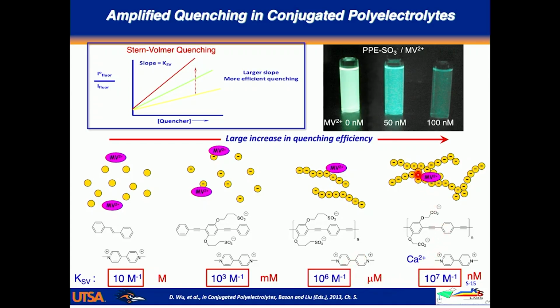And it turns out under certain conditions where these polyelectrolytes are aggregated, which is pretty common, you can see these Stern-Volmers go into the range of 10 to the 7th to 10 to the 8th. So you can get really, really high quenching constants. And that now means that in terms of sensing, you can detect things like this viologen in the low nanomolar range. And just to give you an idea, visually what this means, this is our polyphenylene ethynylene sulfonate. These are actual photographs of solutions of that polyelectrolyte with 0, 50 nanomolar, and 100 nanomolar viologen. And you can see quite visible quenching, which is very easily detectable by using spectrophotometers. So this is the idea of amplified quenching. It allows you to measure these effects at really low concentration.